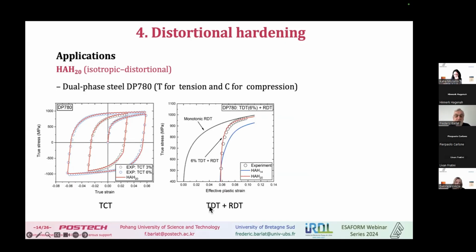If we do transverse direction tension plus rolling direction tension, then again, we do some pre-strain. So the experiments on the pre-strain only are represented here. This HAH20, the last version of the HAH model, captures the experiments quite well. The blue line was the former model, the previous model, HAH14, and we had a small problem here, and this is one of the reasons we tried to improve to HAH20.